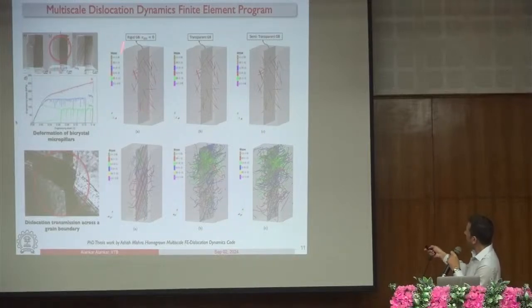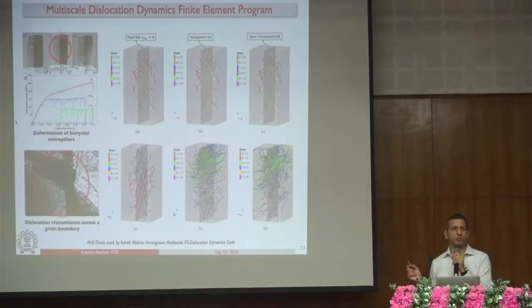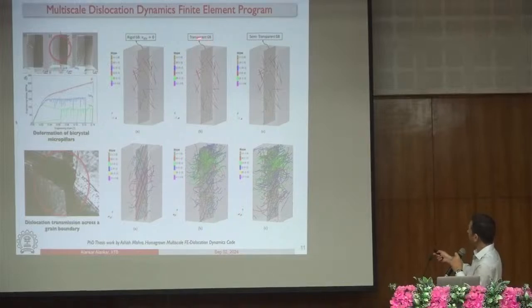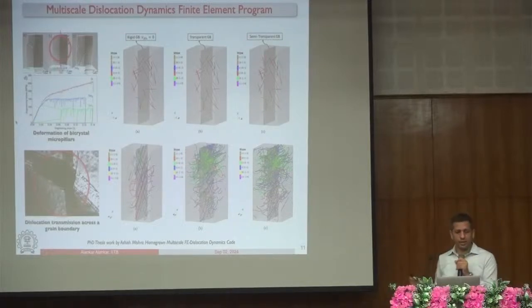The first one is a rigid grain boundary simulation. That means as soon as the dislocations hit the interface, the velocity will become zero, right? And there are transparent grain boundaries. The dislocations can completely cross the boundary, and there are semi-transparent. That means there are some dislocations already existing at that. These are also very expensive simulations.